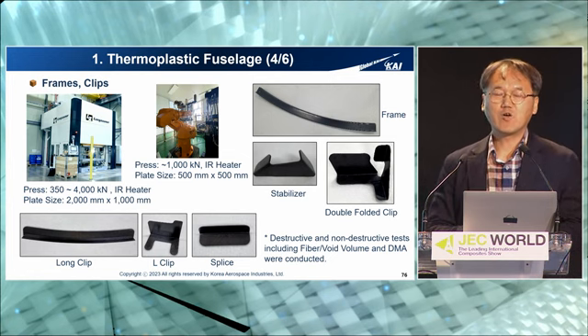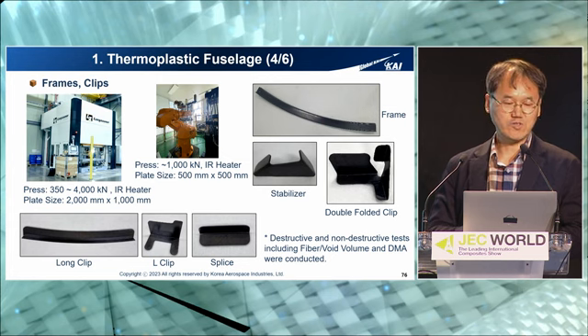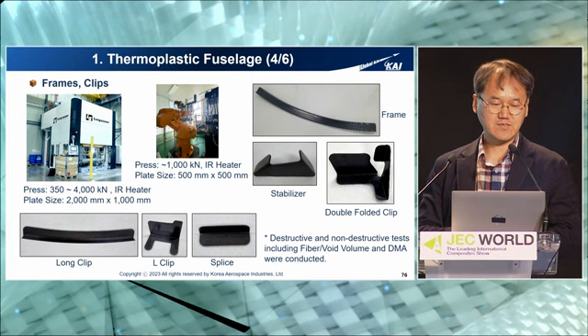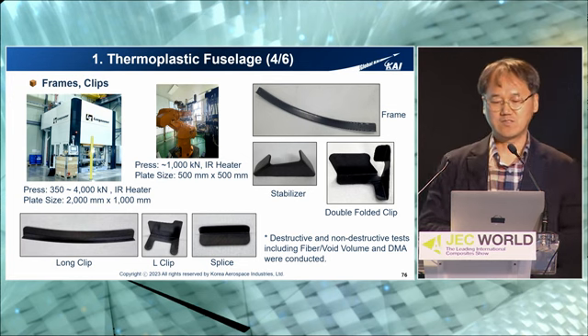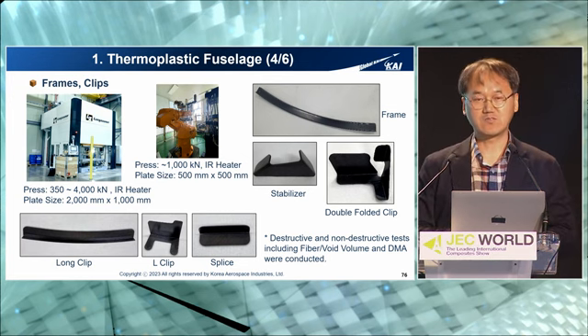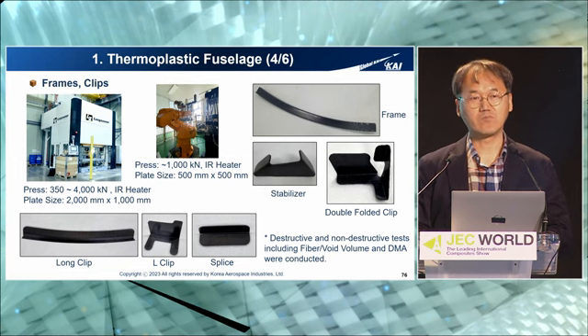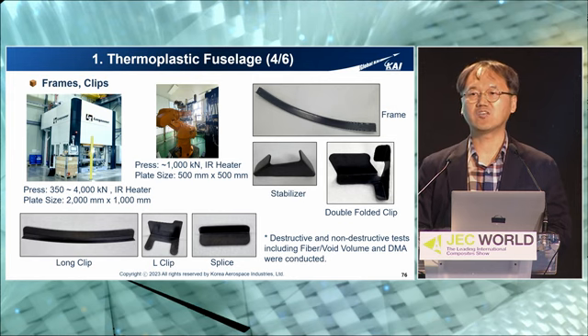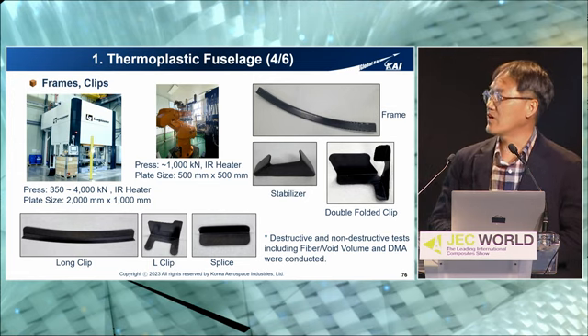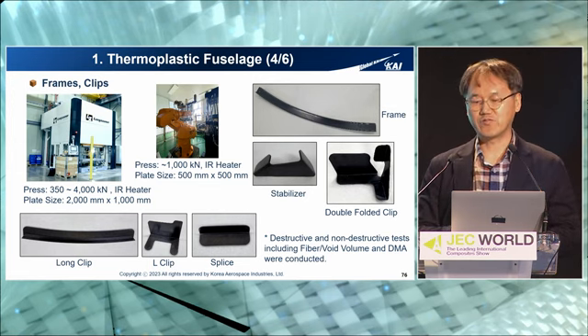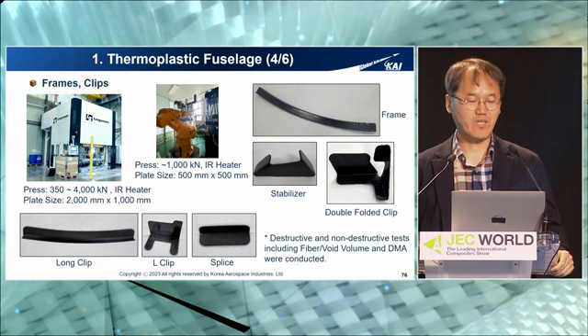For the frame and clip manufacturing process, we used 2 kinds of press. The bigger one is a 400-ton press, with a 2 meter by 1 meter bed size. The smaller one is 100-ton, with a size of 0.5 meter by 0.5 meter. Both presses have IR heaters to give high temperature just before applying pressure. KAI is developing several kinds of configurations, such as frame, stabilizer, double-folded clip, long clip, and L-shape.